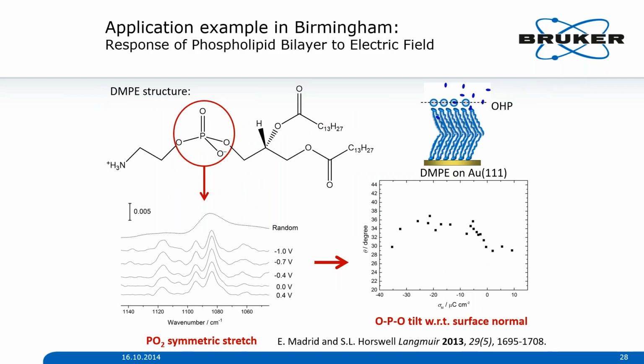The last slide about interesting applications for electrochemistry is studying the orientation of molecules on the surface of an electrode. The beauty of infrared spectroscopy is that you can see not only chemical composition, but also the structure. If the structure formed on the electrode is well organized, like these phospholipid bilayer molecules, the bands become much narrower, and you can judge whether you have a random orientation or a more organized layer, based on the width of these bands and also their position. From that, you can also calculate the tilt of these molecules to the surface layer normal.